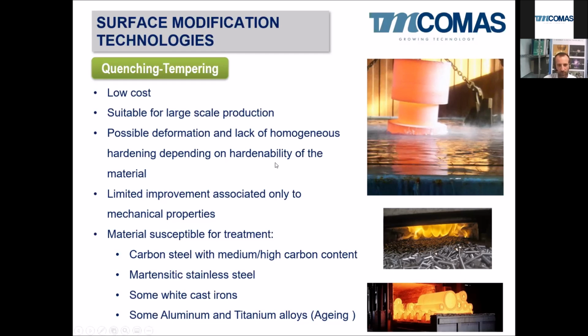Also, we have to be very cautious because all the properties that we want to modify with quenching and tempering are limited to mechanical ones. So, except for some exceptions, we cannot dramatically improve the corrosion resistance or the wear resistance by these quenching and tempering processes. What materials can be treated? Carbon steels with medium and high carbon content, martensitic stainless steels, some cast irons, and aluminum and titanium alloys through the effects of aging processes.